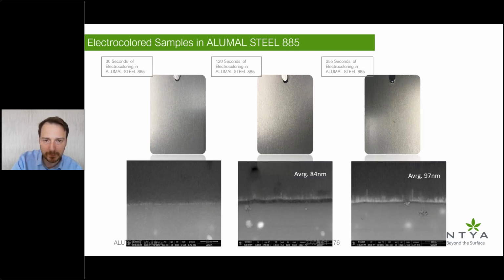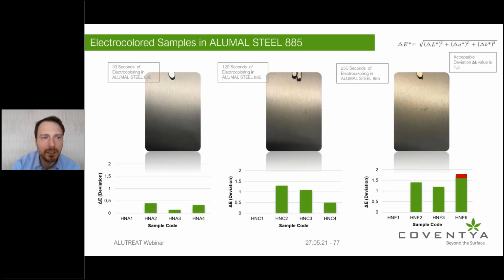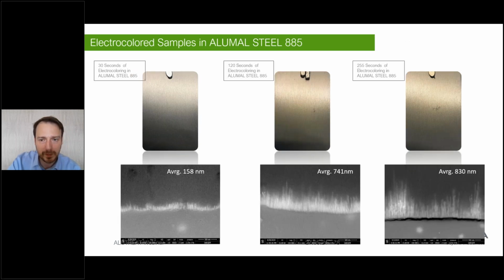You can see here, although the amount that we are precipitating is again for stainless steel color, so it's even a lighter shade than champagne, close to 100 nanometers, it is much more controllable because, quite frankly, the time you need is almost 2 minutes, and the change in L value or the precipitation from 120 seconds to 250 does not change drastically. Therefore, yes, you can never get black with this system, but it gives you a much wider range so that you can adjust the color accordingly and you can get repeatable results. As you can see here,